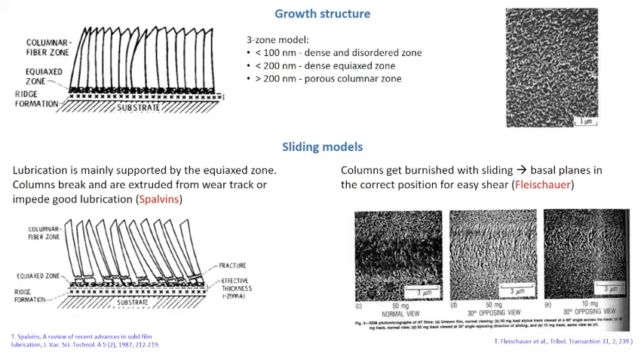And in this case, the film that you can generate can be sketched with this model, which has been proposed by Spalvins, where the first layer here is formed by more or less 100 nanometers of a dense and disordered zone. And the truth is that this first layer presents not really good tribological performances. But if you go further in the deposition, you have the generation of another layer composed by a dense and equiaxed zone. And in this case, you can see very good tribological performances, so low friction and low wear.